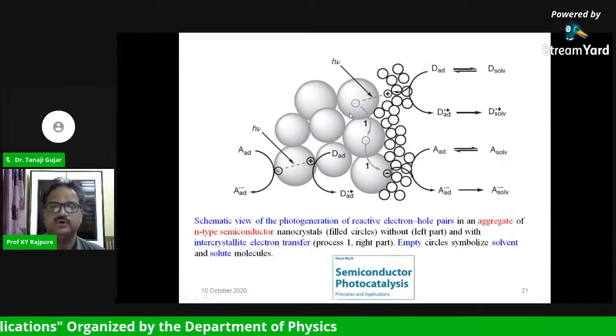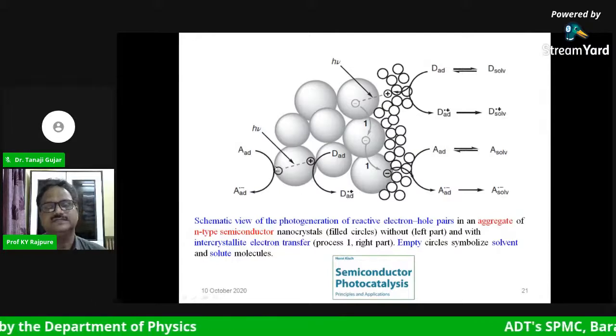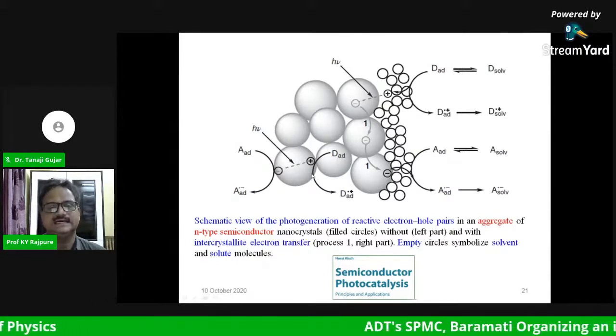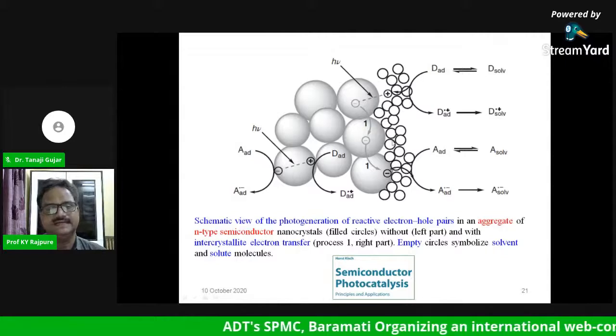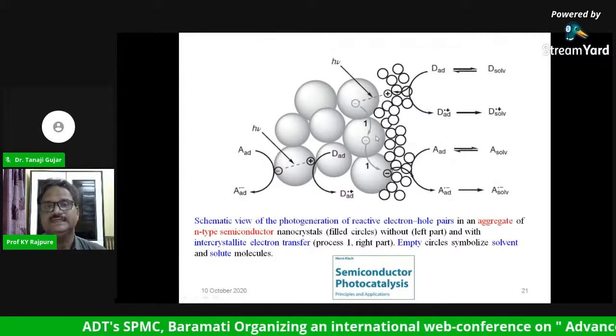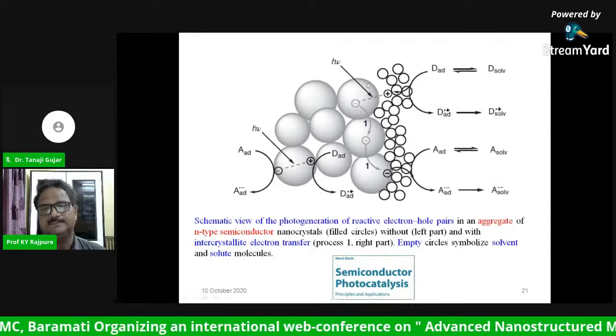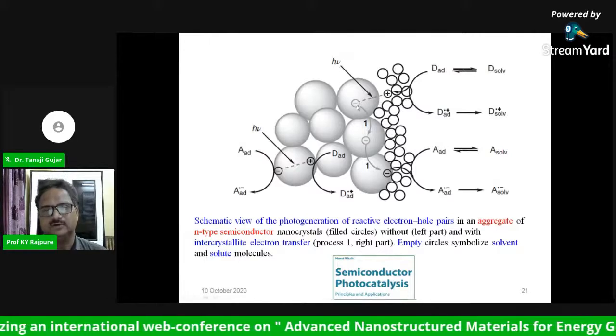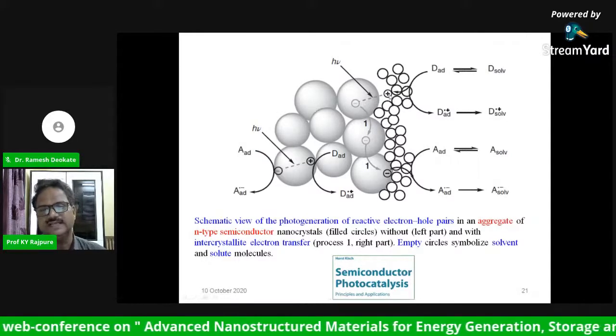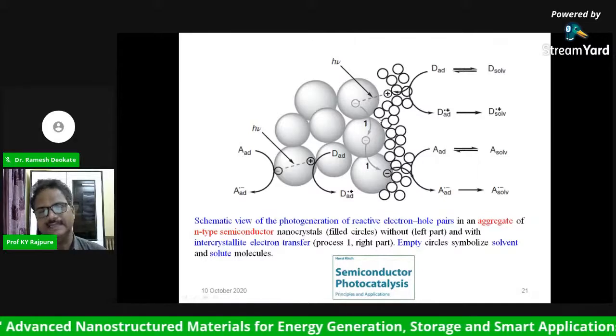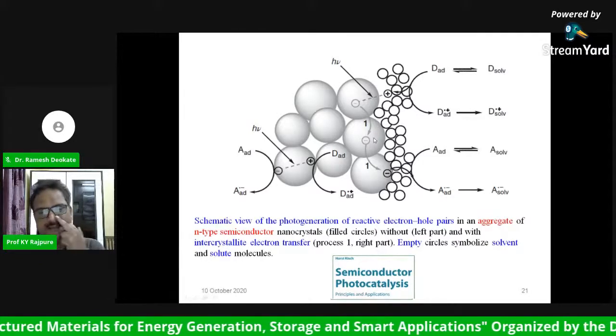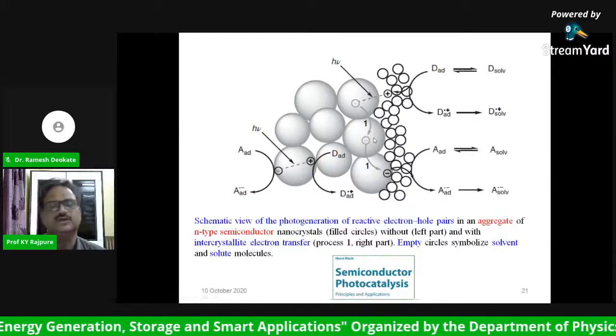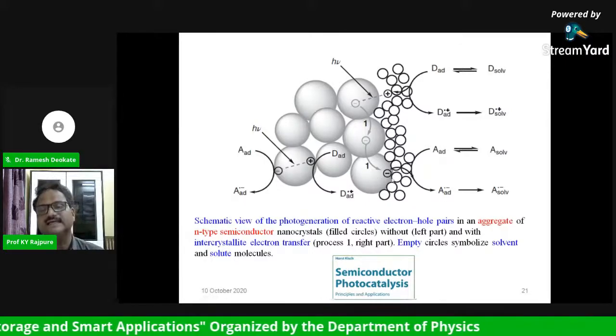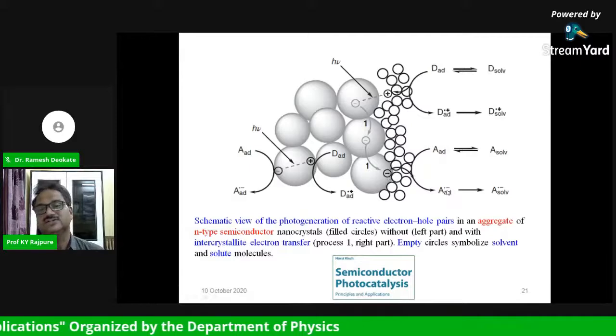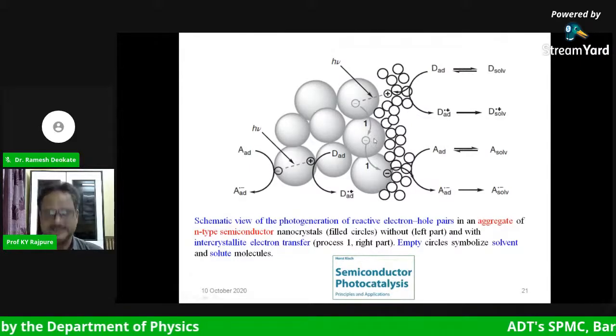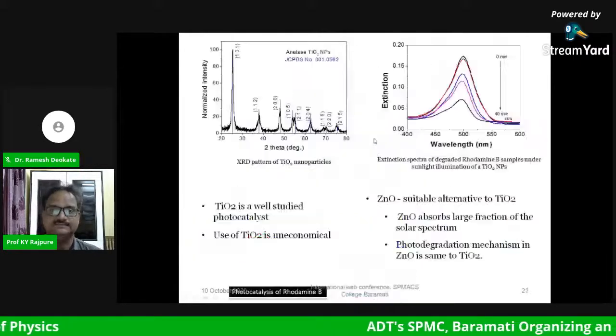and if it is aggregated, then the whole surface of the particle is not in contact with the polluted water. Then the reduction and oxidation do not occur in the same way in an aggregated n-type semiconductor, for example. One particle absorbs the photon, and an electron and hole pair are generated. The hole is utilized here for oxidation, and the electron goes via the intercrystallite electron transfer process to another crystallite and reduces. So this is a very important aspect which we need to understand.